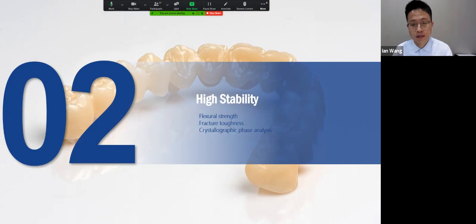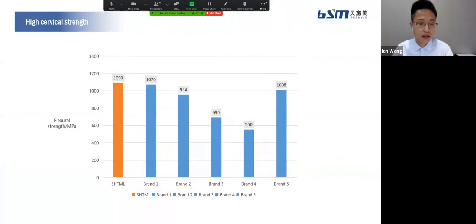Okay, after the first part about the premier aesthetics, we know the stability for a material also is very important. So in the second part, I will share the high stability of SHTML from some important technical parameters. And we compared our SHTML with other 5 popular multilayers on the market. And the first parameter is the flexural strength. We made the same samples from the same height of the blank, and we do the same test, and this is the result. And we can see among all the samples, our newly upgraded SHTML has the highest flexural strength.